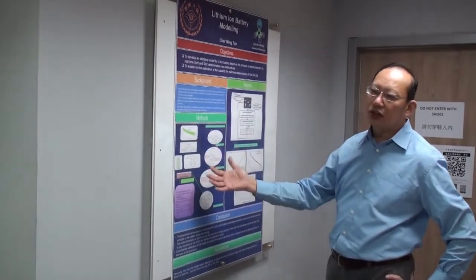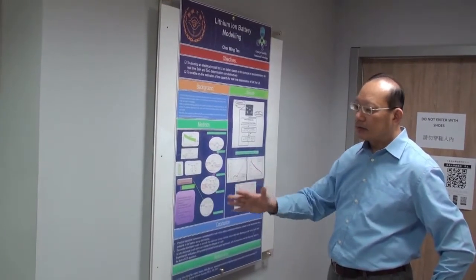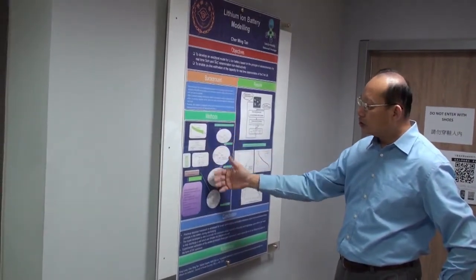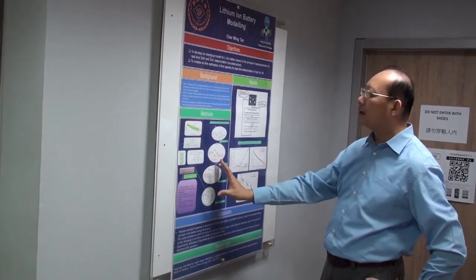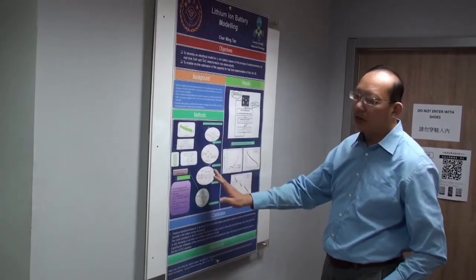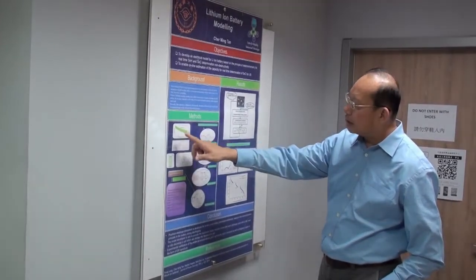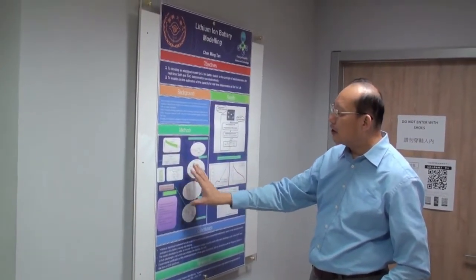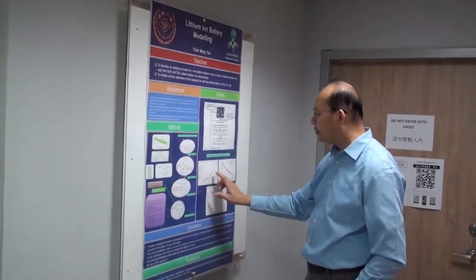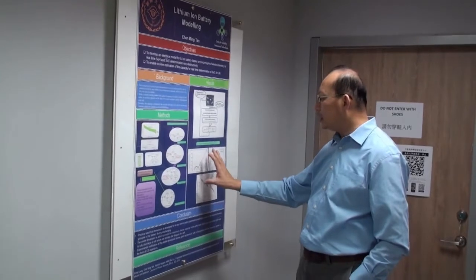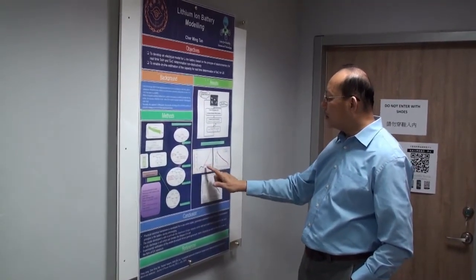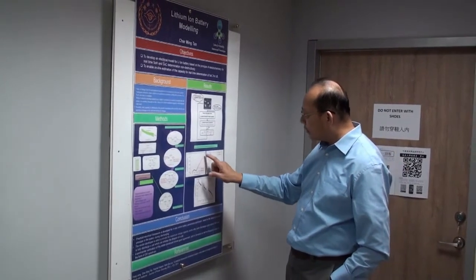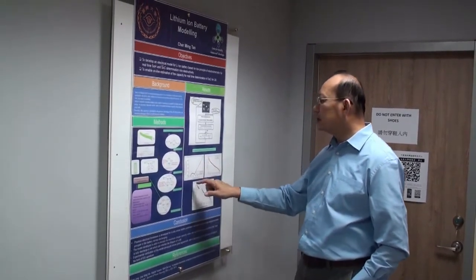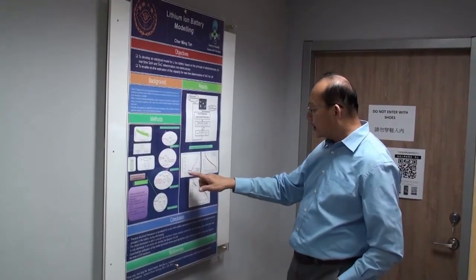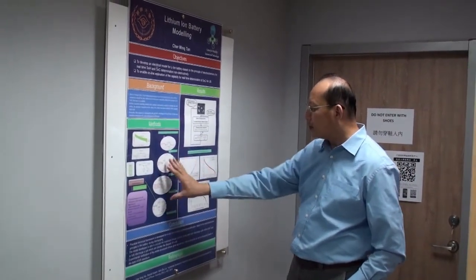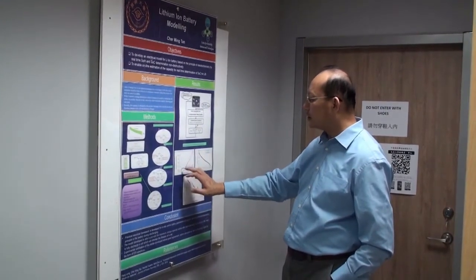Because the maximum charge they can store will actually decrease after many charge and discharge cycles. This is a method which is very fundamental, based on electrochemistry, and it can work for all batteries. Once we get this equivalent model, we are able to evaluate what the impedance of this battery will be. With this impedance, you can see that the blue points represent the experimental result of the EIS, whereas the red one is calculated from our model. You can see how good a match it is.